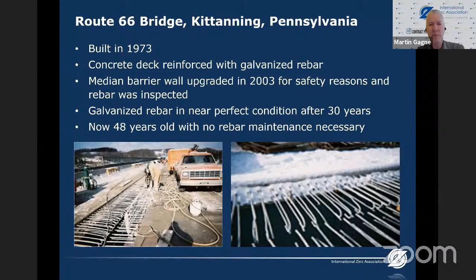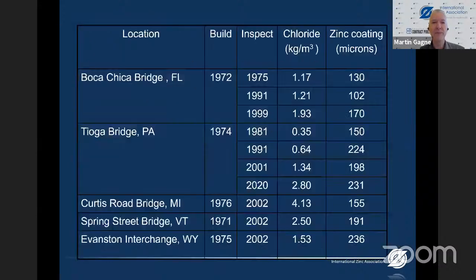And the bridge was built with galvanized reinforcing steel, and they found that the rebar was still in near perfect condition after 30 years. So they just cast the new concrete right over the old rebar. Again, if another corrosion resistant coating such as fusion bonded epoxy had been used, it would not have been able to withstand that demolition process, and more reinforcing steel would have had to be added for the project. And now this project is approaching 50 years old and still no rebar maintenance required.